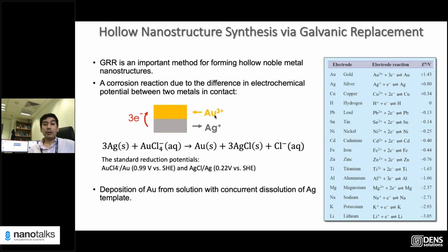The mechanism behind it is very simple, right? Etching or corrosion occurs when you have two different metals, or one metal and the salt of another metal, in a solution, and when they come into contact, because of the difference in electrochemical potential, the metal with a higher potential, the more noble metal, can deposit on the surface, and then when it reacts, it can take away more atoms. So essentially the metal with a higher electrochemical potential deposits on the surface and then corrodes the one which is less noble. Here I'm showing just the reaction for gold and silver.